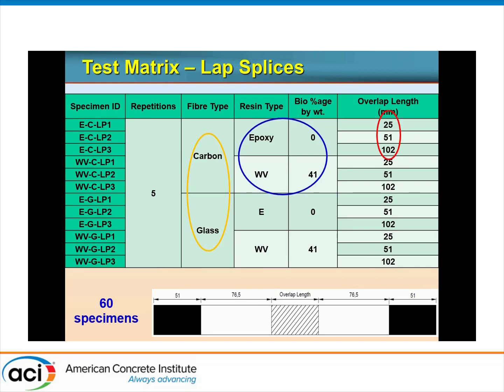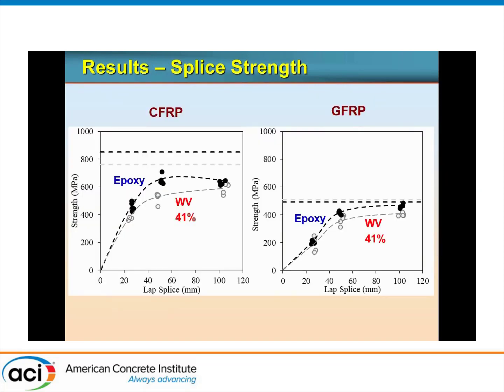So we examined only the WV wood and vegetable byproduct resins. We compared with epoxy, and we varied the overlap splice using coupons again from 25 millimeter, or 1 inch, to 4 inch. Again for carbon and glass, and 5 repetitions. Again, within the limited scope of this study, here are the results. That's the strength versus the lap splice. The horizontal line is what we got from the tensile failure of the coupons in the previous phase. And clearly, again, you increase the capacity, but you don't actually quite get to the full tensile strengths up till 4 inch.